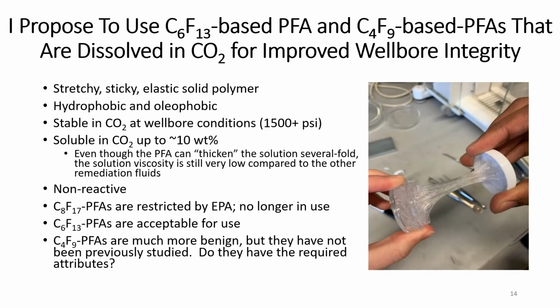So the question is, what exactly are these PFAs like? PFAs are stretchy, sticky, elastic polymers that don't dissolve in oil or water. They are stable in CO2 at wellbore conditions and soluble up to about 10% in carbon dioxide. Their C8 variant is the most thoroughly researched, but is restricted by the EPA, so we are focused on laying the groundwork for the C6 and C4 polymers, as they have been shown to have less of an environmental impact than the C8.